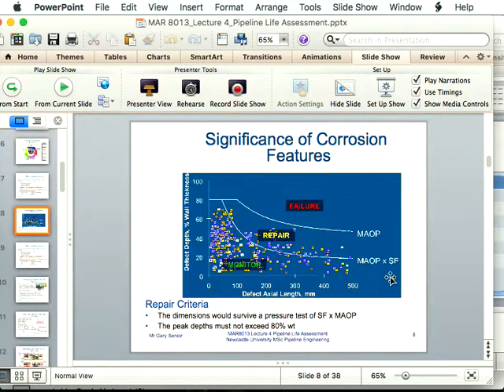That curve there is calculated from ASME B31G, which determines the defect limit of the depth and length combinations for the pipeline's MAOP. It then applies a safety factor: beneath that MAOP, draw the line again. If our safety margin is 30%, for example, then the second line is plotted. So what it's saying is that from a pipeline operator and integrity manager's view, we are happy with a 30% safety factor. Therefore, any features below that line, we're not interested in repairing. We don't see them as an immediate threat. But any above, all of these ones in here, then we would actually be repairing them.